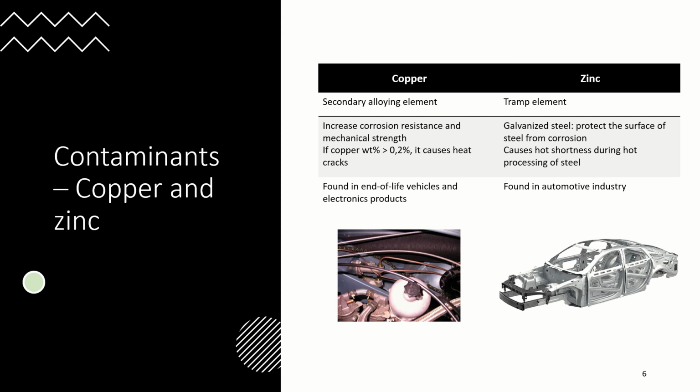The contamination of copper is mainly from end-of-life vehicles and electronics. Zinc is a tramp element and gets into the steel through a process called galvanization in order to protect the surface of the steel from corrosion.